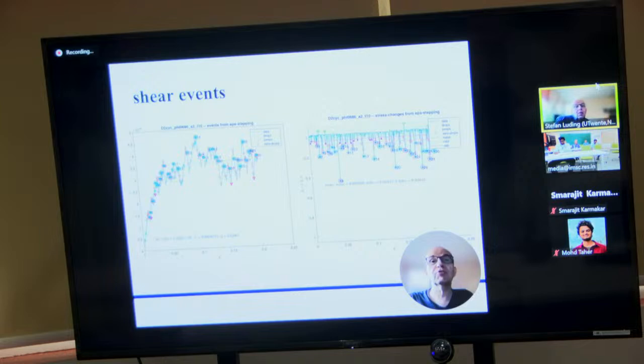In order to understand what is going on in a stress-strain situation, left plot is stress-strain, as we saw it before. We want to analyze it. So we have a MATLAB script which is taking all the stress drops and numbering them, and then we can do statistics based on the stress drops. So in the left plot you see stress-strain, as we had before. In the right plot you see delta stress over delta strain, which gives us the elastic shear modulus. That's the horizontal level here. It gives us the stress drops which are going negative, and it gives us a few rare events which are going slightly positive, at least for a short time. So that are stress jumps, but they are very rare. Stress drops are the normal thing which are happening, and they are happening at different magnitudes at this point.